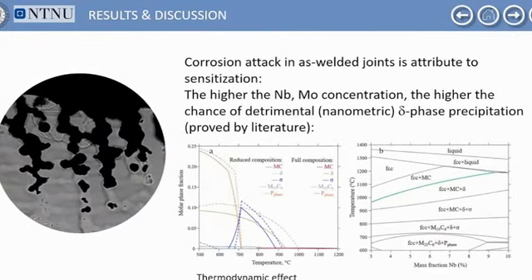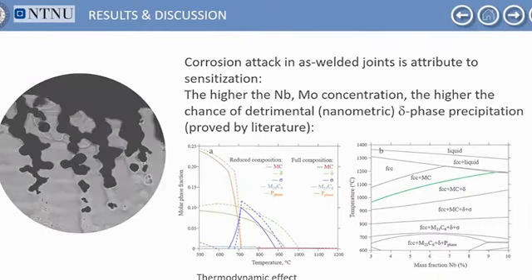Okay, about the discussion, we have postulated that in the interdendritic zone we have a precipitation of secondary phases. Delta phase precipitates in the interdendritic zone with a nanometric size. This was also observed in literature, and this is the problem of the corrosion, or the sensitization, of as welded joint.